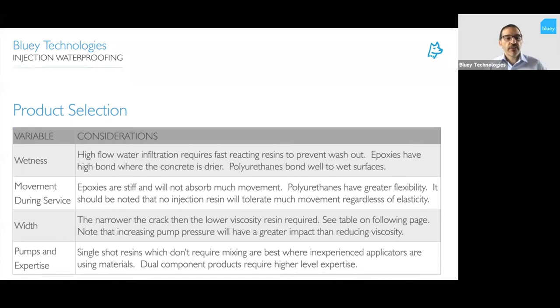So product selection will come down to a few things. Wetness: when you have a high flow of water, you need a fast reacting resin to prevent washout. So it has to react fast, bond to the surface and stop that water from coming in. Epoxies typically have higher bond where the concrete is drier. So an epoxy is used for a dry crack. Polyurethanes will bond well to a wet surface.